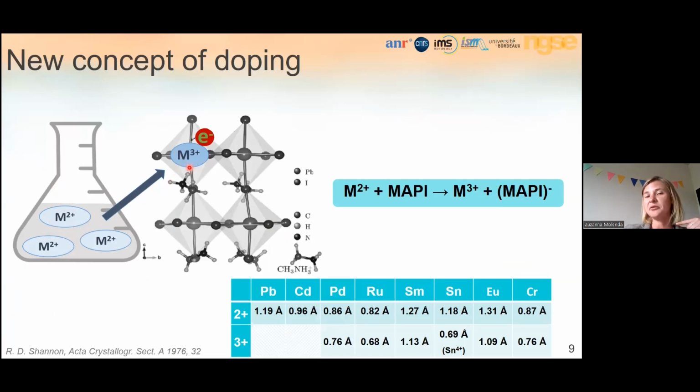So once introduced into the perovskite crystal structure, it would oxidize to 3+ and release 1 electron to the conduction band. This electron obviously would increase the electron density, leading to the shift of the Fermi level, leading to the N-type semiconductor. So this sounds great.